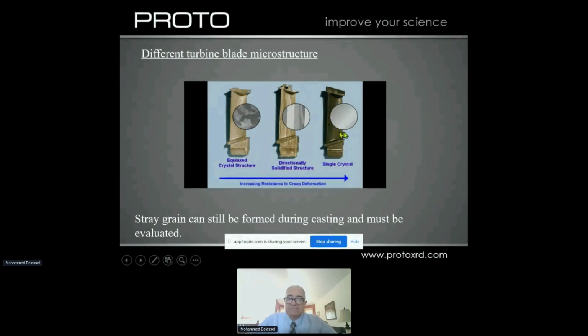And going to a better structure, they went with single crystal, where we have one grain for the whole entire blade. Although they manufacture these blades to be single crystal, sometimes they may get what they call stray grains that can grow from the bottom or inside in the middle. It depends on a lot of physics like thermodynamics, and these can be problematic. But of course, some of them, if they exist, can be thrown out, and some of them may be accepted depending on the misorientation of that grain. They have all kinds of criteria to accept or reject it.